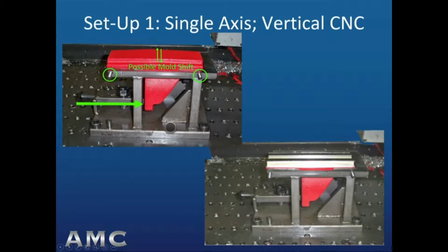The image at the upper left is marked up with one concern for this casting mold design. If the mold were to shift in the direction of the green arrows, then the machined dovetails would be skewed with respect to the casting's proper center line. To mitigate that possibility, the casting is clamped primarily against the vertical face between the side gussets. Then adjustable targets with limiting stops are tightened against the fixed targets on the back side of the casting in the same relative positions. If the adjustable targets with their stops cannot tightly clamp the casting side to side, then the mold is shifted beyond the tolerance limit. In that case, the casting is set aside, not machined, and returned to the foundry.